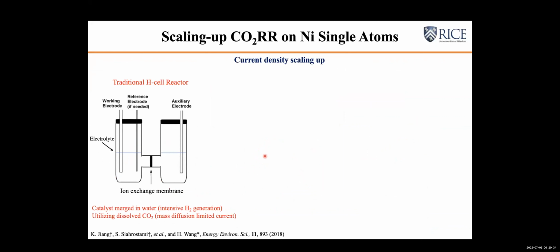And also, once we get the capability of scaling up the materials production of single atom catalysts for CO2 reduction, the next step for us to think about scaling up this process is, of course, the current density. Because we know that in a lot of these traditional H-type cells, we are always limited by current density. Why? This is relevant to the mass transport issue. Because in a traditional H cell, our electrode is actually submerged in electrolyte, and we saturate that electrolyte with CO2. So the CO2 molecule that gets reduced is actually in the soluble phase.